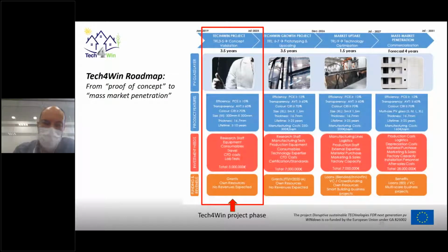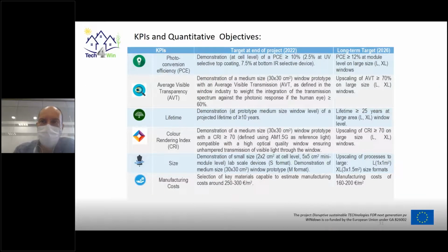So we will focus on what's related to the Tech4Win project phase, even if we have identified not only the quantitative objectives that have to be reached at this phase, but also at every one of the other phases. The main quantitative objectives are summarized in this slide. At the end of the project, in terms of photoconversion efficiency, we want to demonstrate at cell level a photoconversion efficiency higher than 10%, combining an ultraviolet selective top coating with 2.5% of efficiency with a bottom infrared selective device with a 7.5% efficiency. We also want to reach very high transparency.